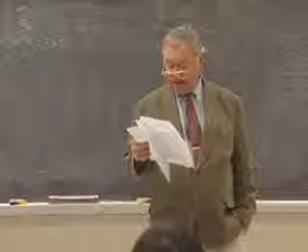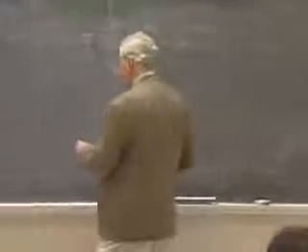Then there is one other equality that depends on structure. And this is something known as the Cauchy relation. And it depends on the interatomic forces. The first condition that has to be met is that the forces between the atoms should be central forces. What is a central force? Well, this is a case where the attractive force between the atoms is directly along the line joining their centers.